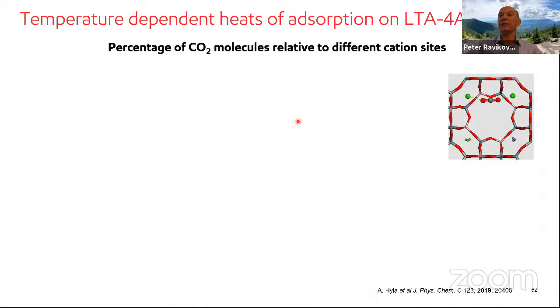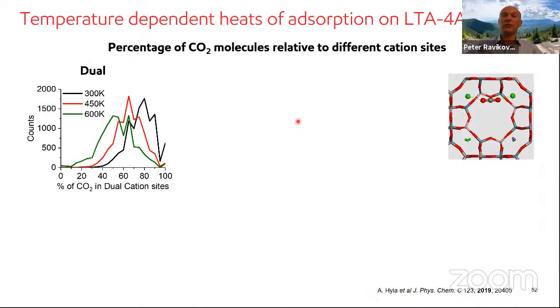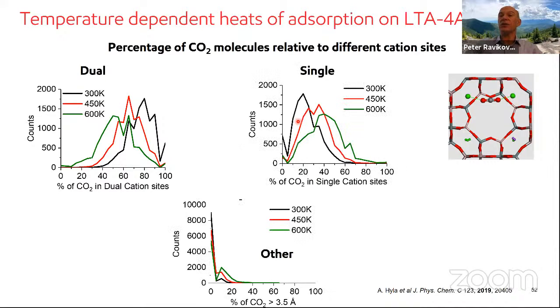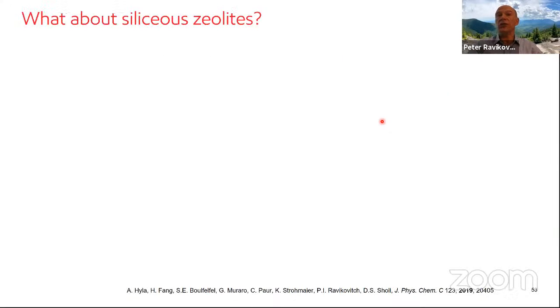It turns out that if you plot the histograms of each individual site as a function of temperature, you find that there is a shift. So in other words, at the lower temperatures, the population of the strongly interacting dual and single cation sites is higher than at higher temperature. So as our temperature increases, the molecules move from these strongly interacting sites and interact less strongly with the zeolite. So this gives rise to the difference in the heat of adsorption with temperature.